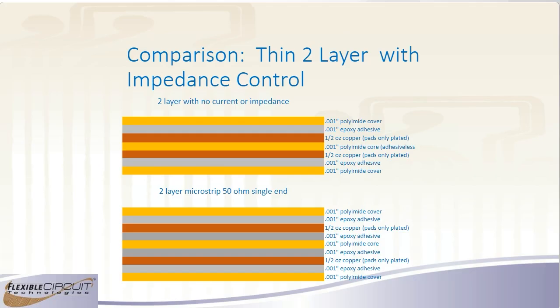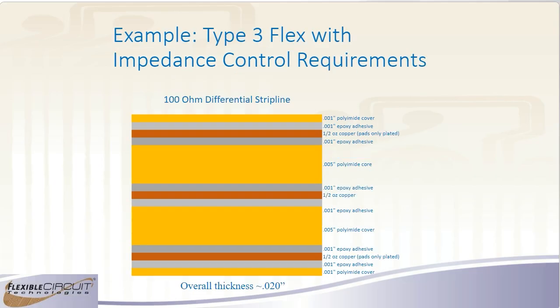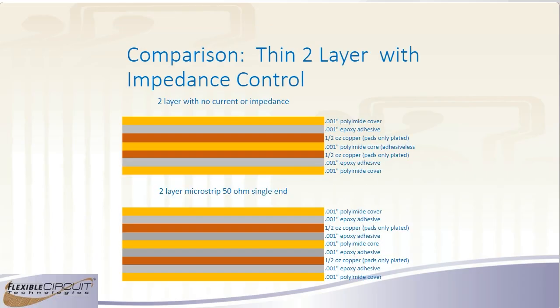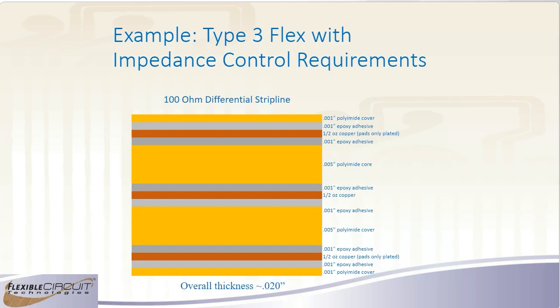If we had to go to a strip line construction and we use the same 50 ohm requirement or 100 ohm requirement, we're looking at almost 2.5 times the thickness of the previous one. So I mean, it's a huge difference. And I'll scroll back again so you can see you're going from no requirement to a single 50 ohm strip line up to 100 ohm differential with planes on both sides in the strip line. So it's going to make it a lot thicker.